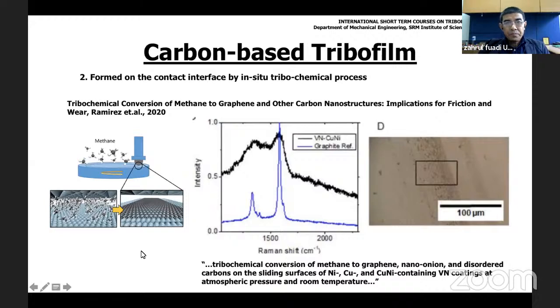And here, using methane without coating, some kind of carbon tribofilm can also be produced on the contact interface. The tribochemical conversion of methane to graphene, nano-onion, and disordered carbon at atmospheric pressure and room temperature. So it is possible to produce such a carbon-based tribofilm by using in situ tribochemical process.